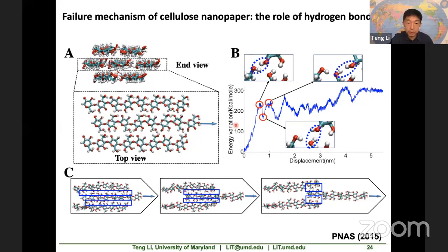So you pull this out among the six and this B curve plots the energy variation as a function of the sliding displacement. You can see that when you start to slide, the energy curve increases. You can imagine all these hydrogen bonds formed between the hydroxyl groups as many little springs, right? When you start to slide, you are stretching the springs and then the strain energy increases. Now, when it peaks, if you further slide, it drops.